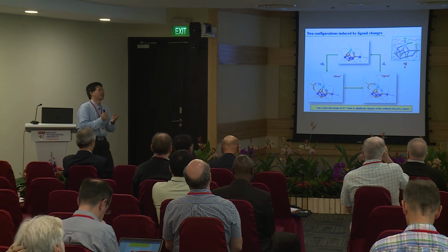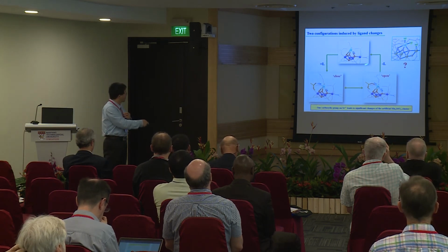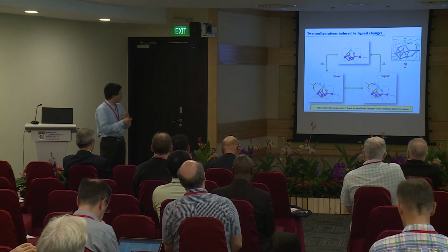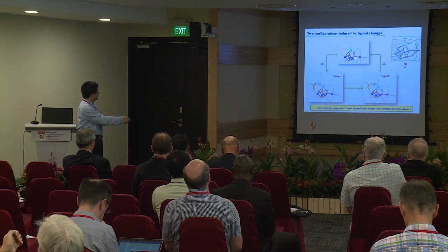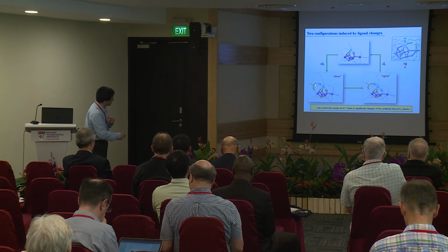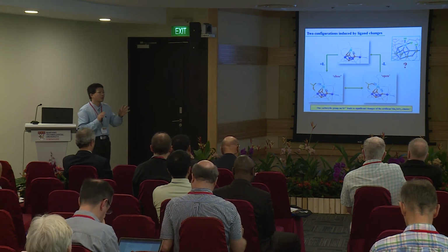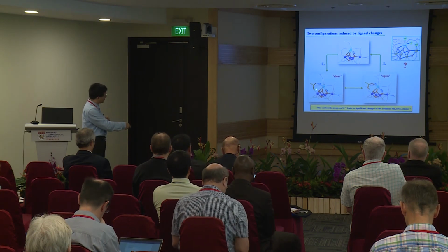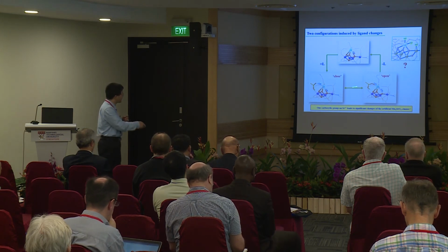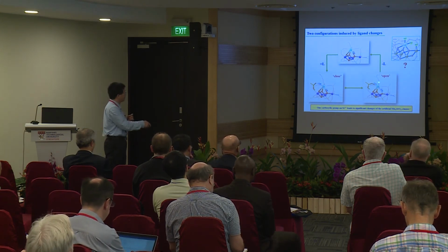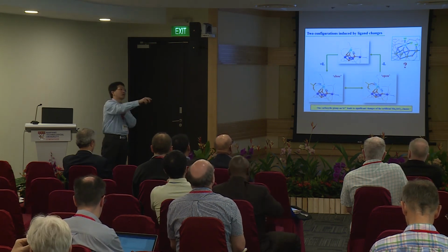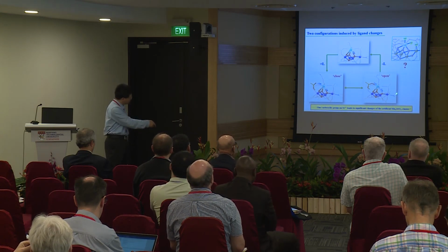Another piece of information: by using this model complex, we can work on what's going on with the ligands. Luckily, we find here we have this model complex. If we introduce one additional acid, just close, we get the crystal structure like this. Basically, the structure is almost the same, but this ligand gets close to the strontium, from 3.4 angstrom to 2.7 angstrom, just bound to the strontium, and that makes this big difference.